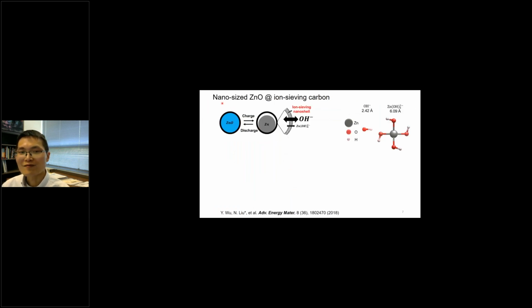So we designed a nano-sized zinc oxide electrode coated by an ion-sieving carbon shell to address both problems I mentioned in the last slide. First, the zinc particle is very small, even smaller than 2 microns, which is the critical passivation thickness. So it will fully convert before passivation happens; it's not thick enough to passivate. And second, the carbon shell acts as a barrier to confine the soluble zincate intermediate inside. So the species inside the particle will not go out and are retained inside. This helps keep the active material in its original location.